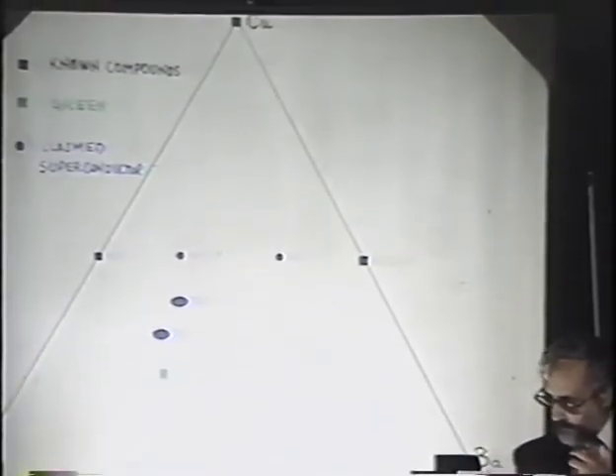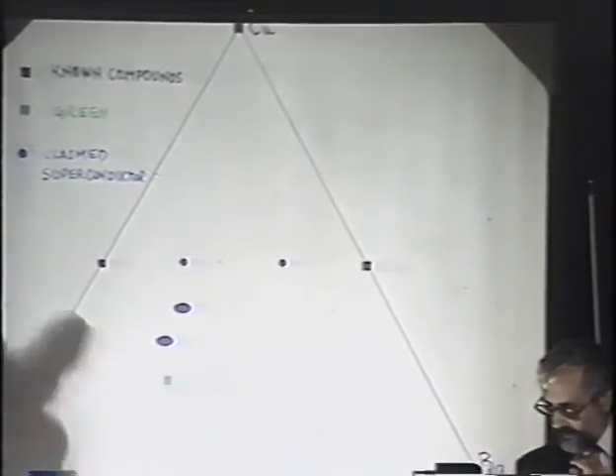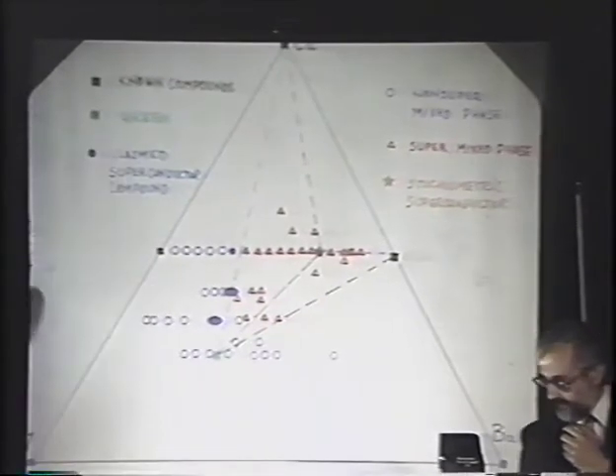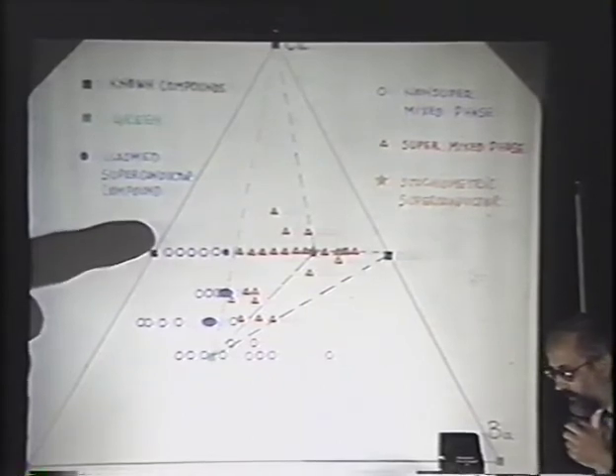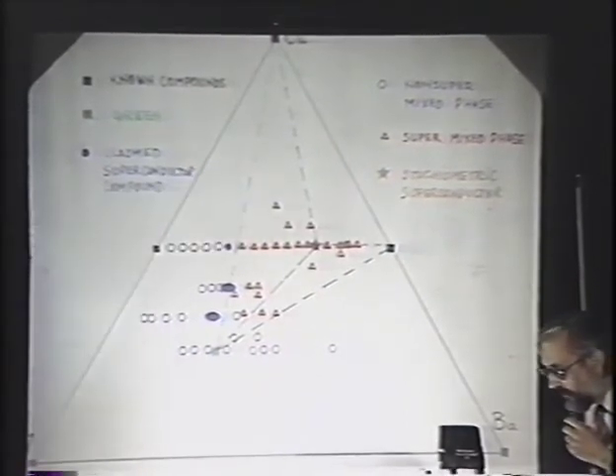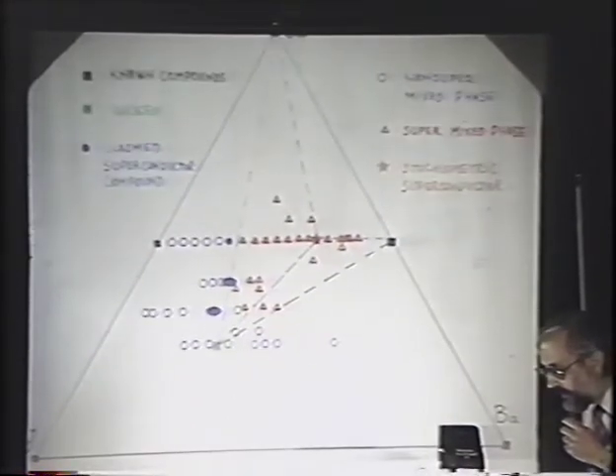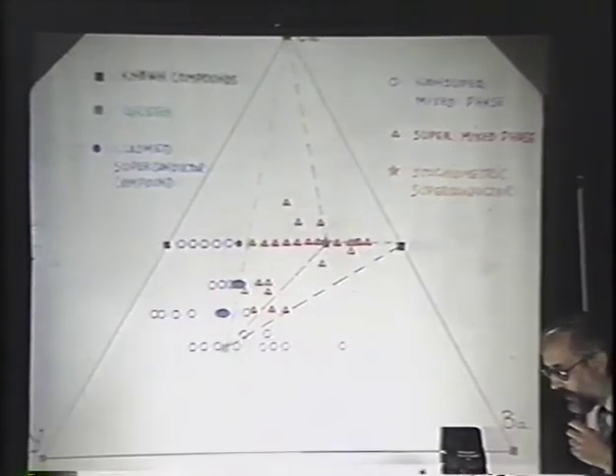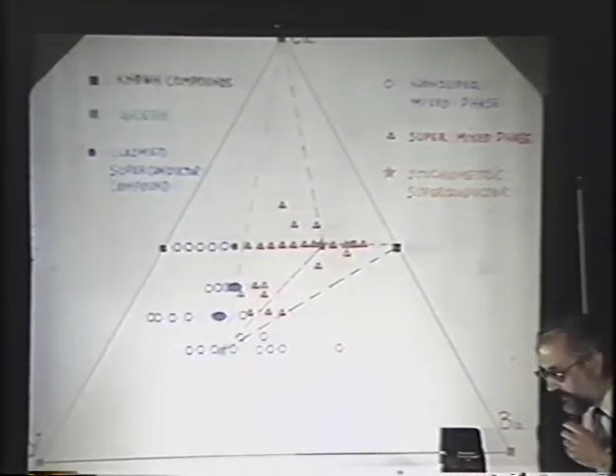In the high temperature superconductor, I want to show you some phase diagram work. Here is a phase diagram to complement what Bertram showed you before. Our people looked at what have been reported as known superconductors, including the green compound and a few other things, and proceeded to make something in excess of 200 compounds, sorting through the ternary phase diagram. The purples are non-superconducting mixed phase materials. The reds are superconducting mixed phase materials. If you look at this in some detail, you can see there are 1, 2, 3, 4 single phase materials, and you can understand quite clearly where all of the mixed phases are. They do all focus on what everyone else seems to have come to as well.